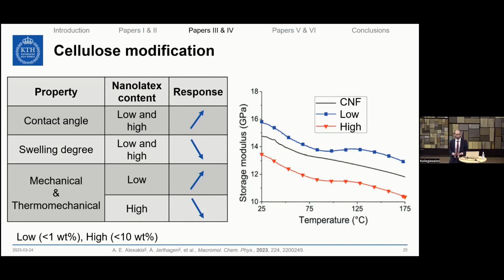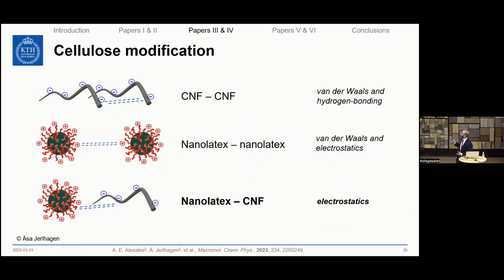In order to understand why that happened, we have to look into the different interactions of the two components that we have in that nanocomposite. So apart from the CNF-CNF and nanolatex-nanolatex interactions, we have the nanolatex and CNF interactions. In these types of interactions, the distance between the nanolatexes in the nanocomposite and how well these nanoparticles are dispersed in this film is quite crucial, because the further away these nanoparticles are from each other, the more the electrostatic interactions between the nanolatex and the CNF are improved, so we can have some sort of a toughening effect in the final nanocomposite. Because these nanolatexes, in a way, act as cross-linking points between the CNFs.